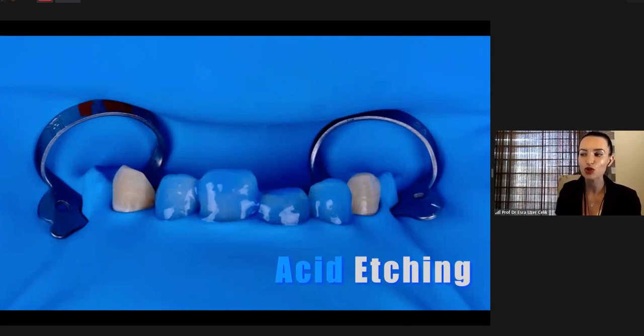Apply the acid gel onto the surface on which you will work. For etch-and-rinse enamel etching, you should apply the acid etching for 15 to 30 seconds in etch-and-rinse adhesives. But when you use a universal adhesive system or a self-etch adhesive system, this period should be shorter, such as 10 to 15 seconds, because these systems also include acidic monomers. So you don't need longer times for acid etching.